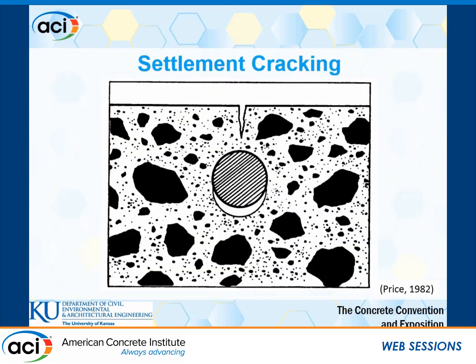The mechanism of settlement cracking has been discussed many times. As the solid part of the concrete settles down and is obstructed by rebar, this action will create a tensile stress in the section above the rebar. When the concrete does settle, your settlement is essentially building up tensile stress.